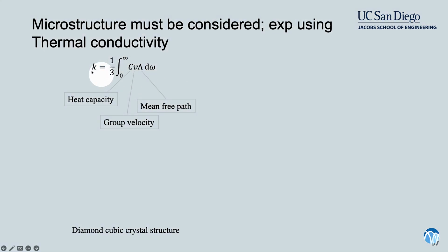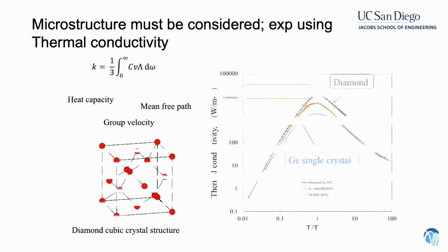So the thermal conductivity, written here as K, can be thought about and calculated from the product of three different things. The heat capacity, so how much heat carriers you can move, how much heat you can move with a given carrier. The group velocity, how fast you can move that carrier, and the mean free path, how long that carrier can go before it scatters, before it changes direction. And you have 1/3 because you're thinking about space in 3 dimensions. So how far you can go before you change directions, how fast you go, and how much energy you're carrying with you.